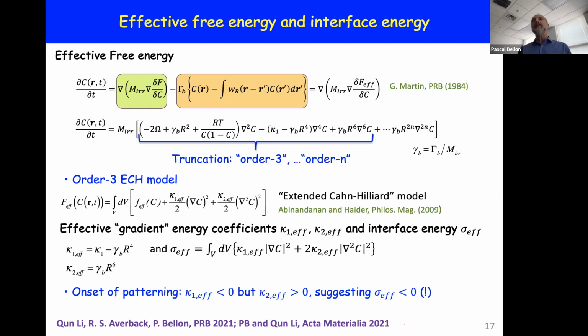But then there are issues, so we cannot use that with Moose, at least not that I know, because it's a FEM implementation of a phase field model, and there are complications. So what we did is a Fourier transform of that expression, then a Taylor expansion of that Fourier transform. So for Gaussian, you end up with a Gaussian in reciprocal space, and then we truncated. Each term of that Gaussian expansion, when you transform back into real space, gives you a differential operator on the composition with power 2, 4, 6, and so on.